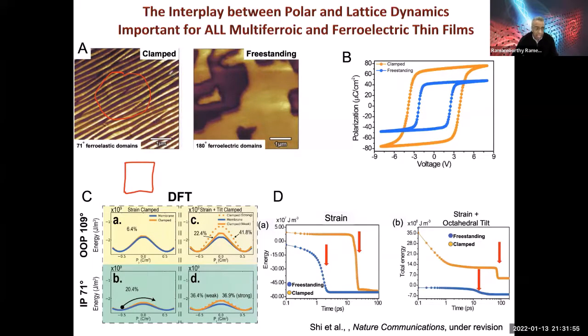So what happens is, in this case, it forms these arrays of 71 degree domain walls where the polarization is doing like this. I'm drawing it in a very crude way, but each one of these bright stripes is a 71 degree domain rotated by 71 degrees away from the dark red stripes. Now, it's forming the stripe-like structure because of the elastic energy component. So when I remove the elastic constraint imposed by the substrate, you're no longer controlled by elastic energy. In this case, the elastic energy is essentially zero. It's a freestanding film, so the only thing that controls it is electrostatics, and it says, okay, I'm going to put a 180 degree domain in the structure. Does that make sense?